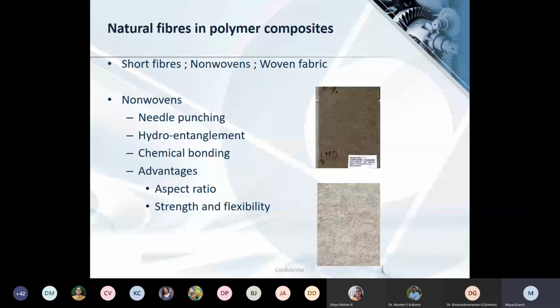Then another technique is hydro-entanglement. In hydro-entanglement, water jets at high pressure and of extreme purity fall onto the fiber mats, and that creates the bonding within the fiber mat. Hydro-entangled non-wovens are very soft and smooth to touch, and they usually have applications as tissues and wipes, diaper linings, and so on. In chemical bonding, you have a synthetic fiber along with the natural fiber, and this mat is passed through a heater where the synthetic fiber, like polypropylene, melts, and that creates the bonding in the non-woven. The advantages of non-wovens are the high aspect ratio, which is the length to diameter ratio, strength and flexibility, and non-wovens are majorly used as interior trim structures in automotives.